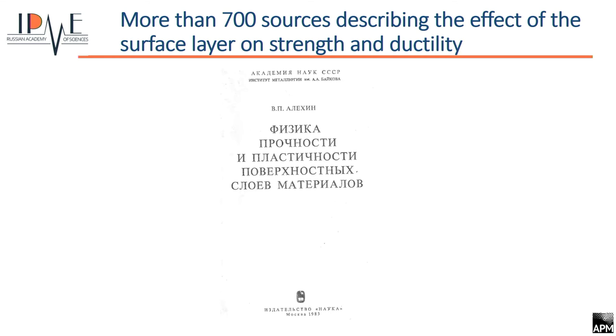So we have in Russian such a book that was published in 1983, and in this book I found approximately 700 sources, 700 papers which describe the influence of the thin surface layer on the mechanical properties of metal. And each time, it is a layer with thickness from 30 to 100 micrometers. During plastic deformation, during the contact with environment, a very thin surface layer is formed that in many cases can determine the mechanical properties of the massive and volumetric metal sample.